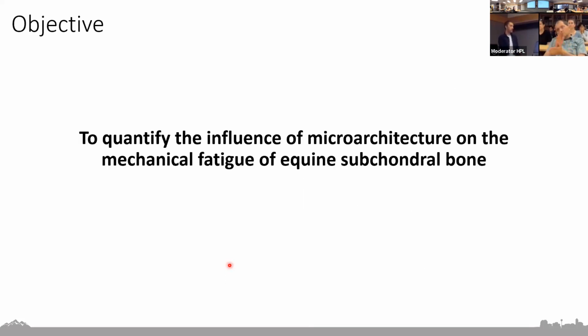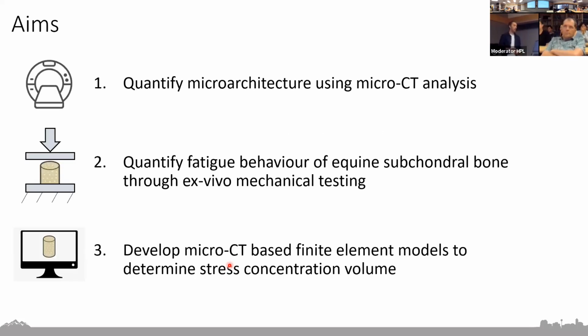So as a result, our objective was to try and quantify the influence of microarchitecture on the mechanical fatigue of equine subchondral bone. So to do this, we first used some high resolution micro CT imaging to quantify the microarchitecture of our samples. We then quantified fatigue behavior through some ex vivo mechanical testing. And finally, we developed some micro CT based finite element models to quantify stress concentration volume.